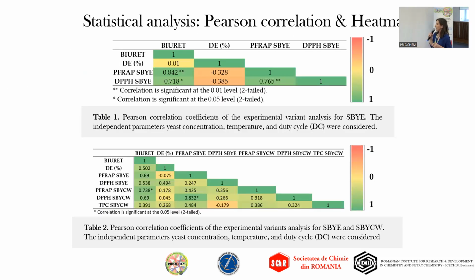A statistical analysis is very useful for this kind of samples to provide a more detailed overview of the data. So we performed the Pearson correlation and heat map using SPSS. First, the Pearson correlation was performed between the samples from the spent brewer's yeast extracts, and we observed that, for example, disruption efficiency is not really correlated with any other assay. The antioxidant activities are significantly correlated with the biuret results, and also the DPPH and FRAP methods are correlated, which means they have the same trend.